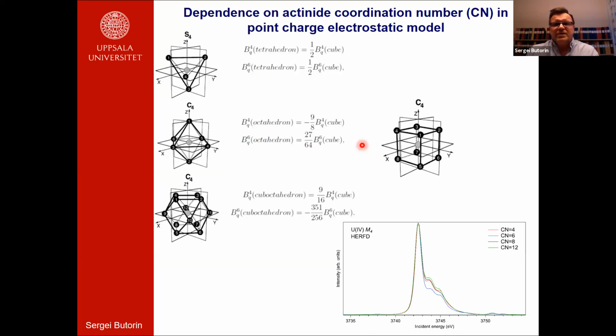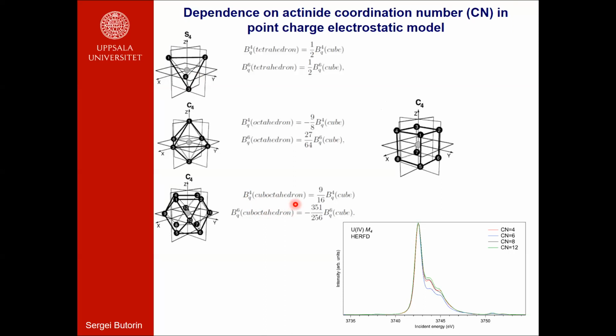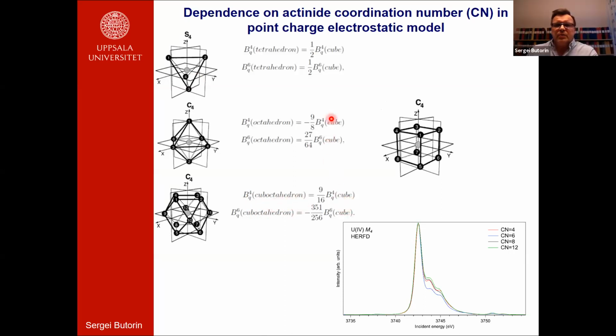So using the point charge electrostatic model, I just set the distance to be the same and the charge to be the same for different polyhedra. And then it's easy to find the relation between crystal field parameters of different polyhedra. As shown here, the crystal field parameters for the tetrahedron and the octahedron are related to the crystal field parameters for the cube. So one can take the crystal field parameters for uranium dioxide and then calculate for other polyhedra. And that's what I did. And the spectra are shown here.